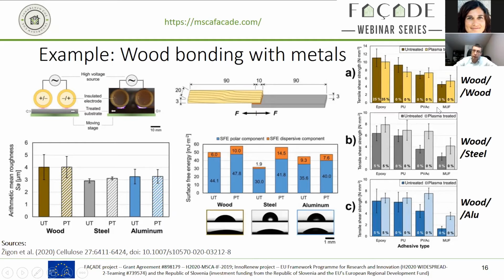But as you can see, even on the steel, we find that the PVAC glue after plasma treatment performed equally well to the epoxy glue without the plasma treatment. So this is something where directly both an environmental and an economic impact will benefit from the plasma treatment.